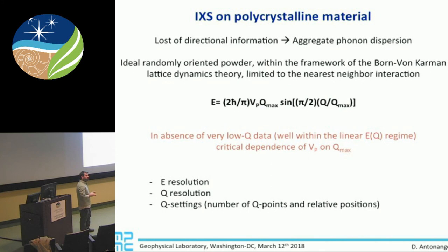The full potential of the technique is obtained while working on single crystals. However, at high pressure, very often measurements are carried out on powder, either because single crystals are not available, or, for instance, like for iron, because the phase transition from the cubic structure to the hexagonal structure disrupts the single crystal. So when working on powder, we have to deal with the loss of directional information, so what is measured is some aggregate phonon dispersion.